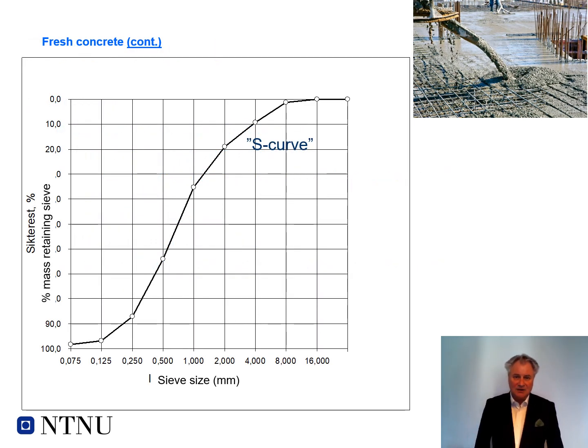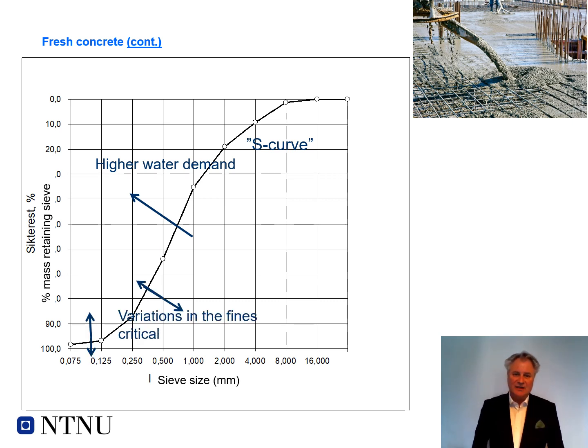So a typical grading could be something like this. For a natural aggregate, it will always have this type of S-curve, as you can see here. And when you have this S-curve, that will lead to a higher water demand in your concrete. But maybe what is even more important is the variation in the fine content of the mix. As you can see here, from around 250 micron and down, we're often talking about filler from 125 micron and down and so on. And if you have variations in this grading, that is of great importance for the properties in the fresh state.